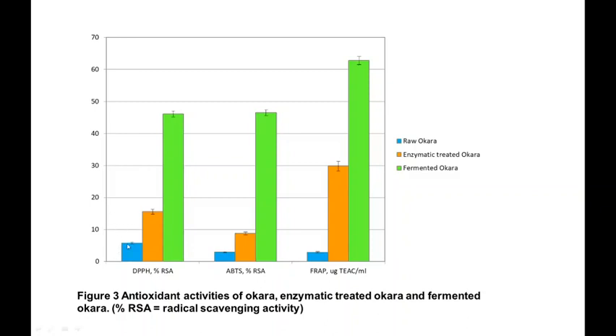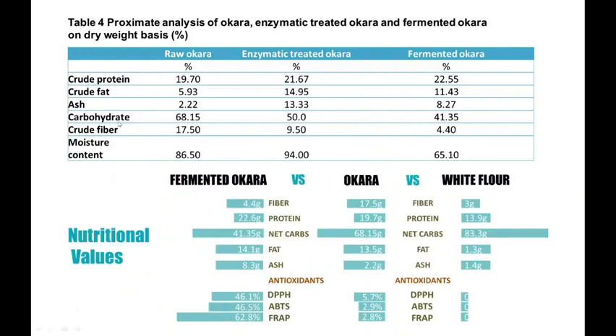From the raw okara, which is about 4 to 5%, it actually increased to about 40+% in the DPPH and ABTS. And for FRAP, it increased to 60 microgram per mL. So we can see that fermentation using the probiotics can increase the antioxidant level in the okara. We also conducted the proximate analysis.